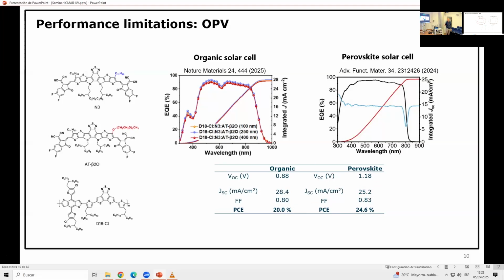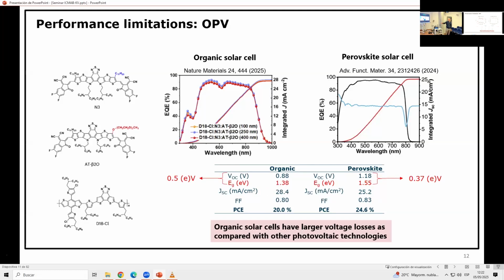So what's the problem then with organic solar cells? This is then the band gap. I put here in red numbers. Okay, the band gap of the organic solar cell is a bit lower, but if you look at the difference between the voltage and the gap, you see that the organic solar cell loses half an eV, half a volt, while the other solar cell technologies don't lose so much. Here in this case, 0.37.